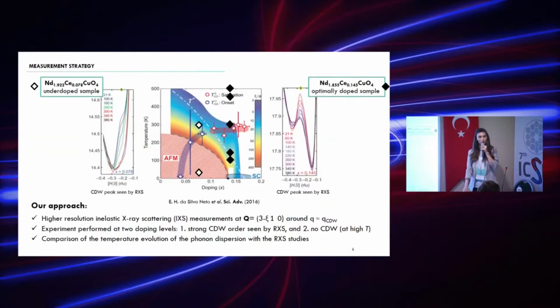So our approach was to choose two different samples, two different dopings, an underdoped sample and an optimally doped sample. Why? Because for the optimally doped sample, the charge density wave peak seen by resonant X-ray scattering, quite a standard method to explore charge order in cuprates, is very prominent here. Its intensity is decreasing with temperature, but saturates around 300 K.